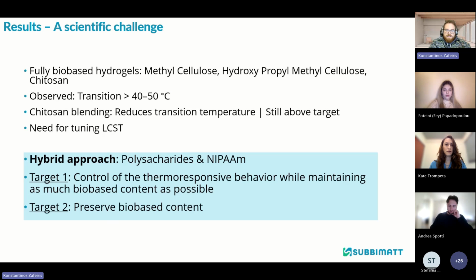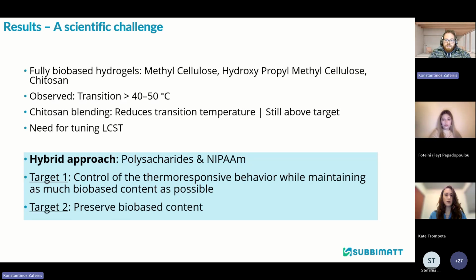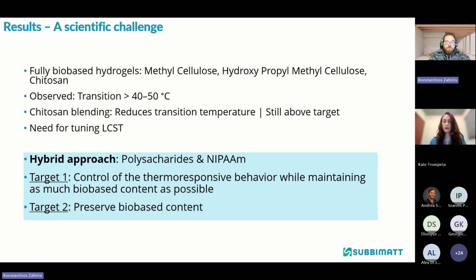So speaking of challenges, this is an interesting challenge that arises from the previous slide and the rheological measurement. Hydrogels comprised solely of bio-based materials have transition temperatures that are above 40 and 50 degrees Celsius. Even with tinkering with the formulation of the hydrogel, we could not reduce this transition temperature drastically.